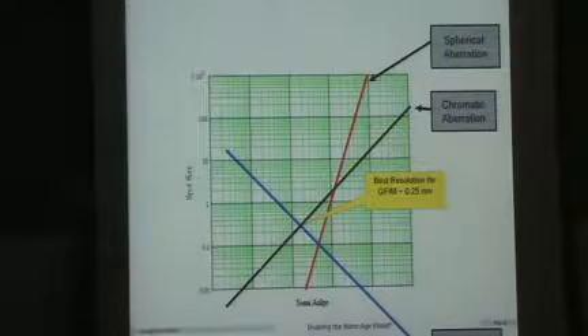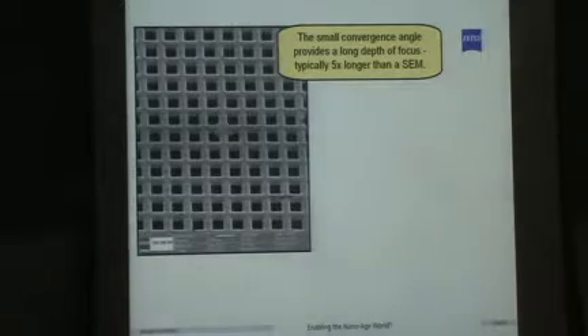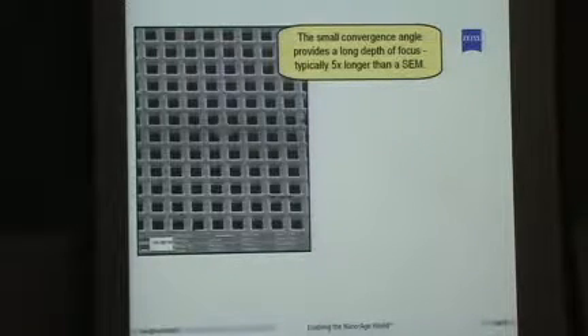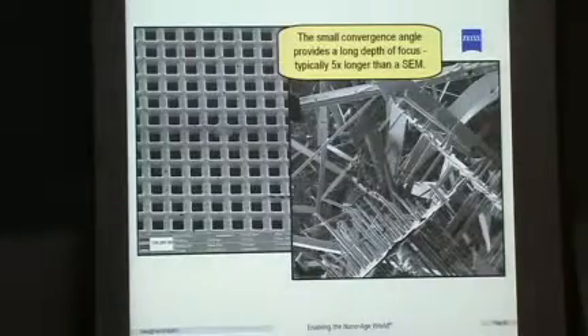But not only that, you'll notice that best optimal point is also at a smaller semi-angle. So we can get a better depth of focus than a SEM. So if you're looking at a tilted grid or a cross-section, you can get a lot of it in focus at the same time. Here's a nice crystal that was grown where you can see features in the foreground and background with a terrific depth of field.